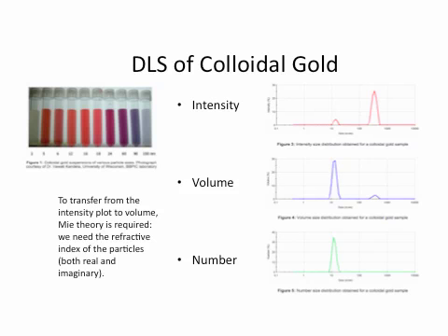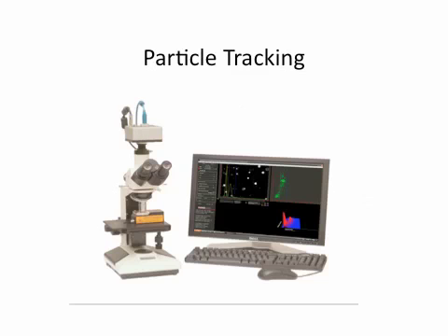So DLS is particularly good if you have a monomodal distribution, pretty narrow, then you know the number you get is the hydrodynamic radius. Because remember also that these particles are in the wet state. Yeah, so if you have some fluffy polymer on the outside, or if you have a double layer with a longer screening length, so a longer Debye length, this particle appears bigger than it is in the dry state. So that's roughly how DLS works.